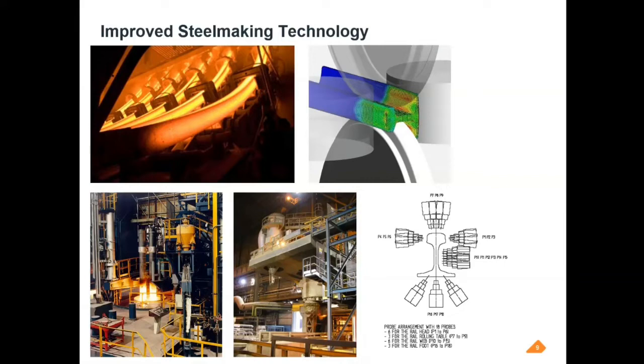The bottom middle picture, it's not a great picture actually, but that's one of our vacuum degassers. So it's a tank with two snorkels on it that we lower into the ladle of steel, about 300 tons, at our ladles at Scunthorpe. Then you suck all the air out of the tank above and take it to a very low vacuum, and the atmospheric pressure pushes the steel up into the tank. And then through one of the snorkel legs, you bubble argon, which lowers the density in that snorkel and causes it to rise. And that creates a current with the other leg of the snorkel, which falls. And you turn over the 300 tons of steel many times in maybe a 30-minute treatment, exposing it all to the vacuum and sucking out the hydrogen that is picked up through the process, and get the hydrogen levels right down. And again, that's very important for reducing the number of rail breaks and improving the safety of the railway.